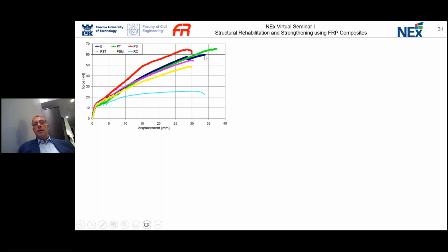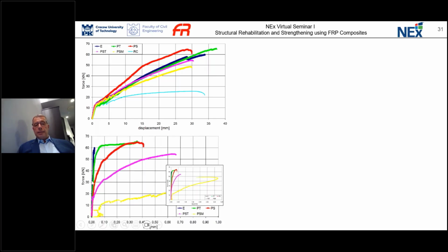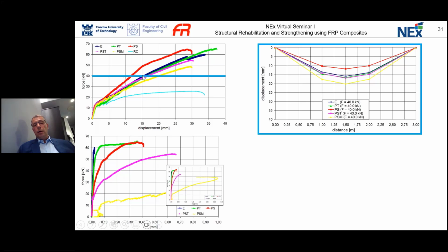This dark blue line represents the epoxy resin. As you can see the slippage at the end of the system, practically there is no slip for epoxy resin, but even a small amount of slippage, 0.3 millimeters at the end of the system for this PS flexible bonding, makes a very big difference and improves the behavior of the structure, even with higher capacity than in the case of epoxy resin. What is also tricky, when we compare one level of the load, you can clearly see that we received even lower deflection using flexible adhesive than when using very high strength and stiff epoxy resin adhesive.